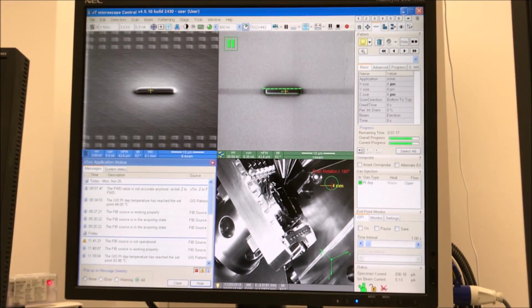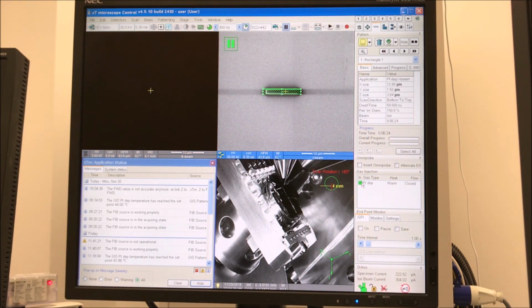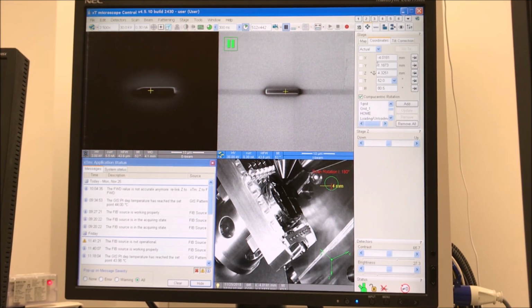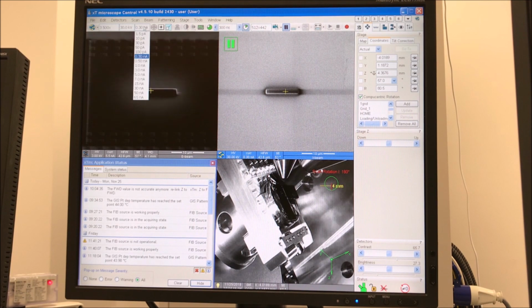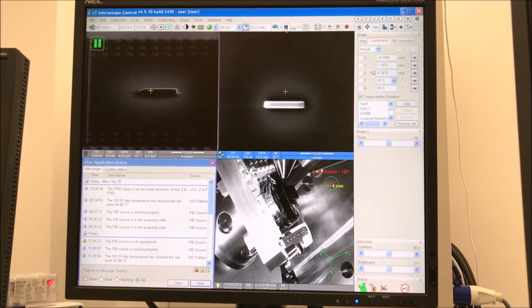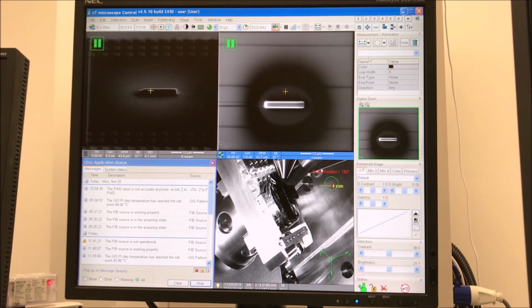So the video is being sped up here because this process is actually quite long. This is about a 6-minute step. So ion beam platinum deposition is done. So now I'm going to retract the platinum GIS, tilt to 57 degrees, and I changed my ion beam current to 7 nanoamps to cut trenches.